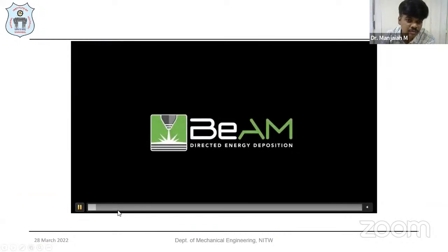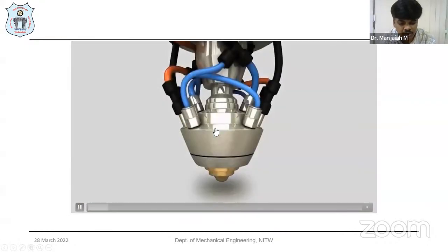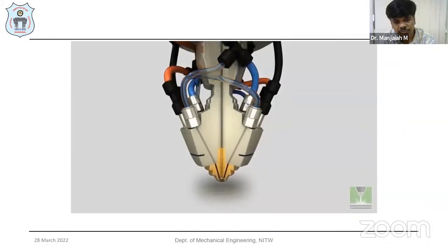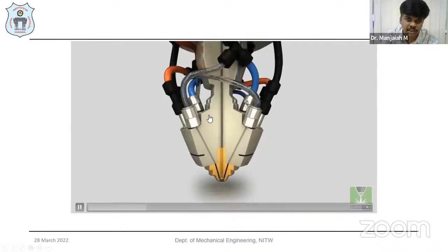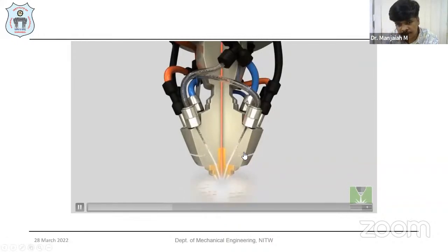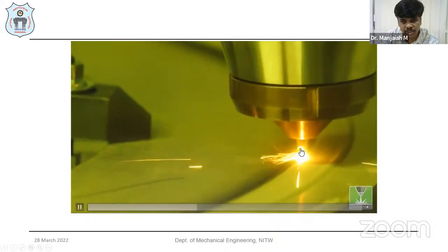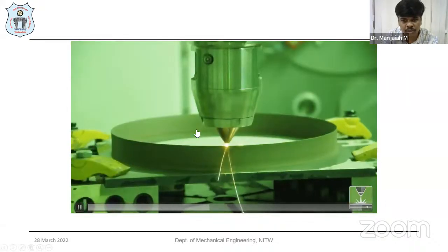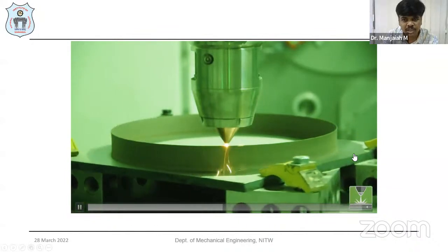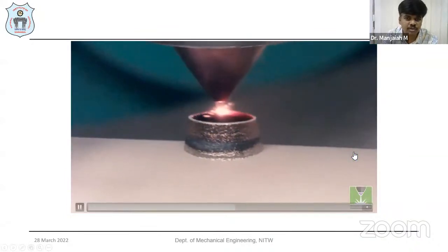You see here how the direct energy deposition process works, from the laser concept or beam technology. You can see from the deposition head, the laser comes from the central axis and the powder is fed through coaxial feeding nozzles. There it interacts with the laser beam, and deposition takes place as a melt pool. This is how layer by layer deposition takes place in direct energy deposition systems.